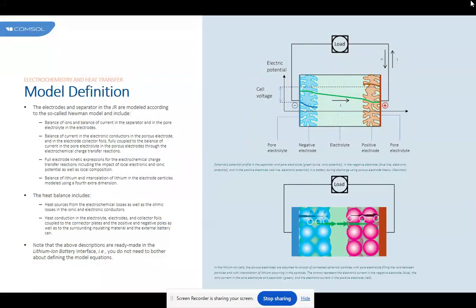Full electrode kinetic expressions for the electrochemical charge transfer reactions, including the impact of local electronic and ionic potential as well as local composition. Balance of lithium and intercalation of lithium in the electrode particles, modeled using a fourth extra dimension. The heat balance includes heat sources from the electrochemical losses as well as the ohmic losses in the ionic and electronic conductors. Heat conduction in the electrodes and collector foils is coupled to the connector plates and the positive and negative poles as well as to the surrounding insulating material and the external battery cap. Note that the above descriptions are already made in the lithium-ion battery interface. For example, you don't need to bother about defining the model equations.